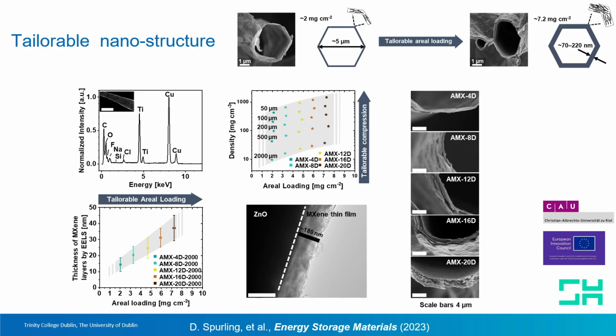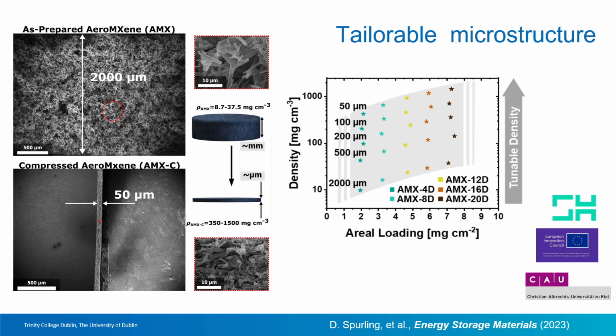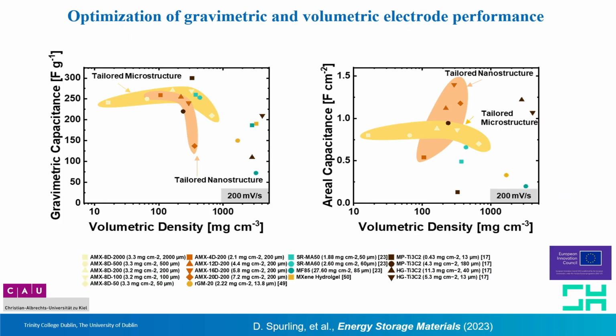depending on the type of performance that you want in your device. But also, we can tailor the microstructure just by applying pressure and making these discs more dense. If you do that, you have an easy tool to control density as a function of areal loading. Then you build a system that can be tuned and templated depending on the type of performance that you want to get out of the device.